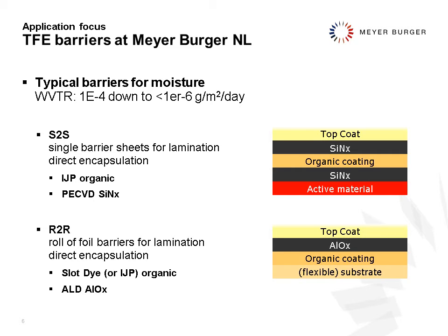Our company can provide a sheet-to-sheet solution. So maybe the willingness to make a single barrier sheet for later lamination, or to directly encapsulate the active device, which is pretty common, or will become more and more common for OLEDs. And to do that, we are using inkjet printing of organic and PECVD coating of silicon nitride. So in the end, we are going to do a device coating which looks very similar to this.